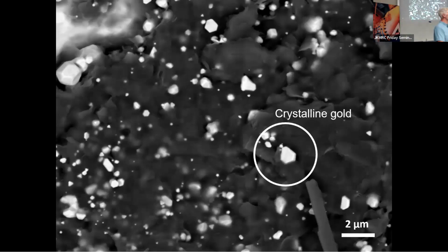Now in this system, gold and silver dissolve, the silver is lost. So that's a different signal than what's going on with gold. A lot of the gold though reprecipitates, and you've got within the circle here, crystalline octahedral gold. You've got the 6 sides of the hexagon plus the top and bottom. So we've got crystals that are growing and it's pure gold. So the primary material will have 5 or 10 or 20% silver or something that's in there. And we've got colloids and crystals that are growing within the system that are pure, that can only be there if gold is dissolved and is reprecipitated in the system.